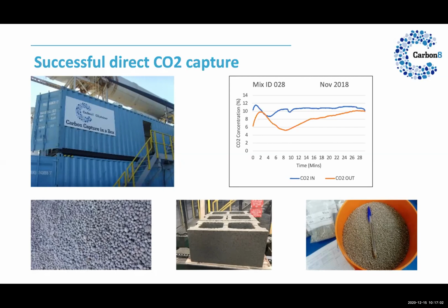And the products we made from that demonstration are typical rounded lightweight aggregate that was used and demonstrated successfully in concrete blocks, which is the typical application of our aggregate. But also, because of the nature of the material, we could also investigate using it as a fertilizer. Benefits of using it as a fertilizer is that a lot of CKD or cement kiln dust in Ontario is already spread on land, but it's a very dusty material, and so it blows away.